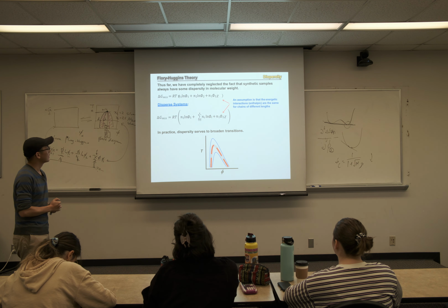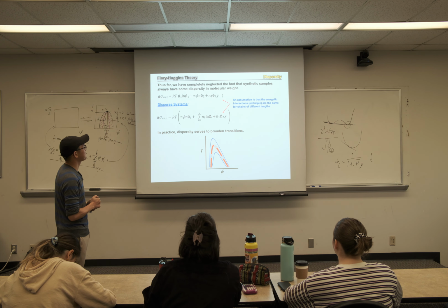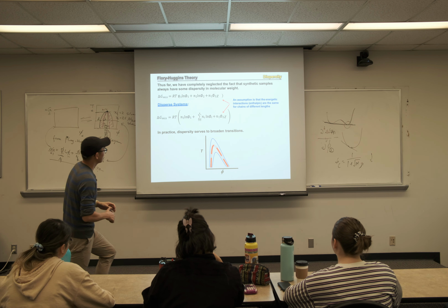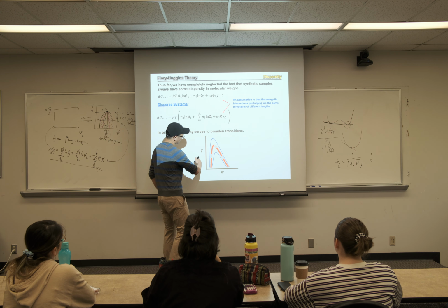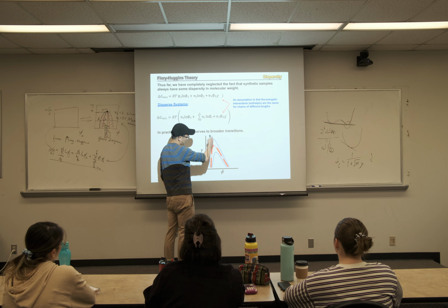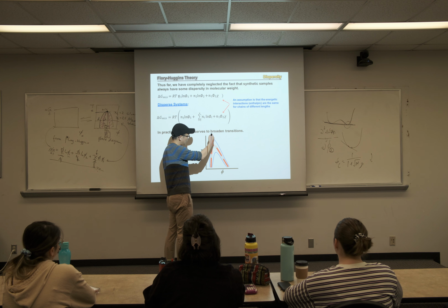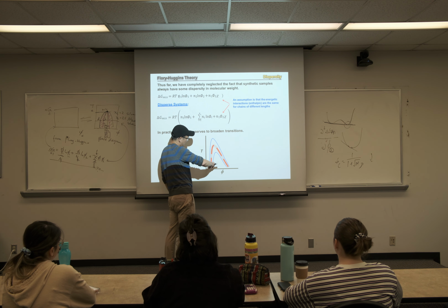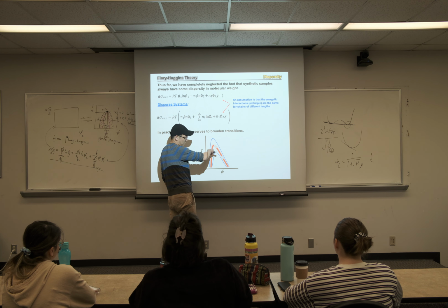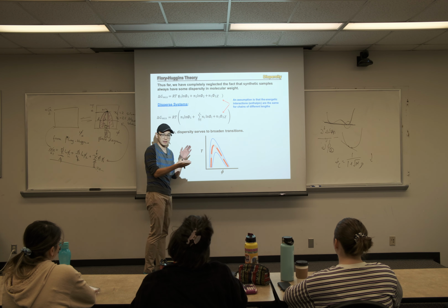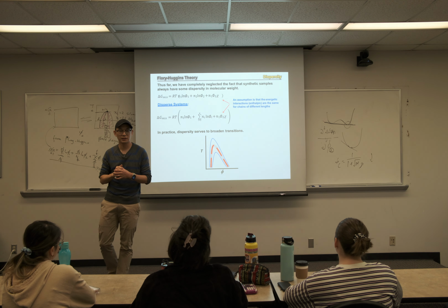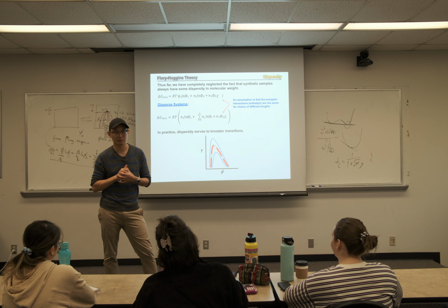This part we have already talked about, right? Generically, if you have a more polydisperse system, you would have a non-symmetric phase diagram, skewed to a lower polymer concentration region, okay? Your boundary will no longer be well defined like a red curve, but instead you have a broader range if you have polydispersity in your polymer.